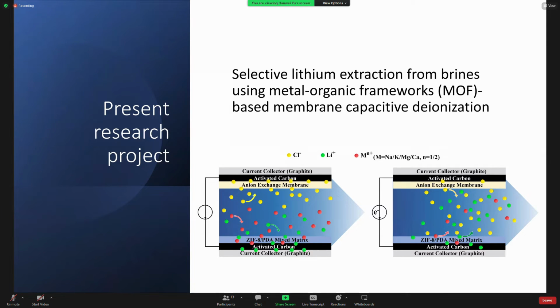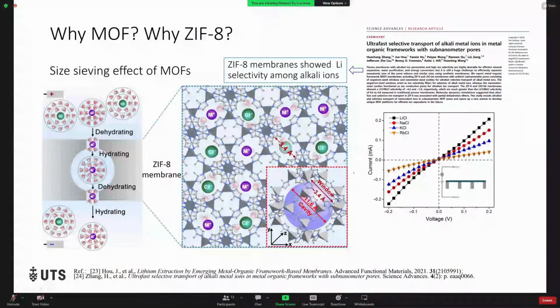to the system, the cations can move towards the cathode. But the ions with large sizes can be blocked by the membrane. Only lithium ions can pass through and temporarily stay in the porous carbon electrode. These ions can be released after applying a reverse voltage. So why did I choose MOF?